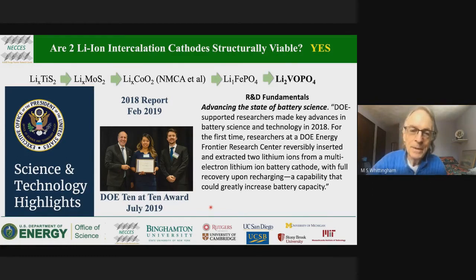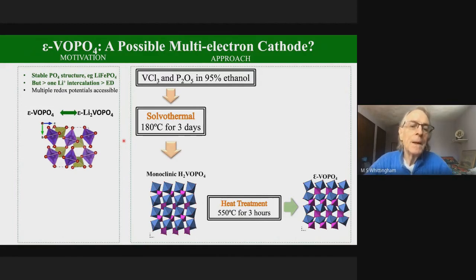It's not finished yet, but let me just briefly show you a little bit of chemistry as to what we did. This is the structure, has phosphate tetrahedra, vanadyl highly distorted octahedra, better described as 5-coordinate. And we made this by a solvothermal approach, mixing a vanadium compound and a phosphorus compound in 95% ethanol. We have to have 5% water in there or it over-reduces the vanadium. And in this case, we've got 2 hydrogen atoms into the structure in place of the 2 lithiums we want. If we heat treat this, we can get those protons out and make a pure phase vanadyl phosphate.